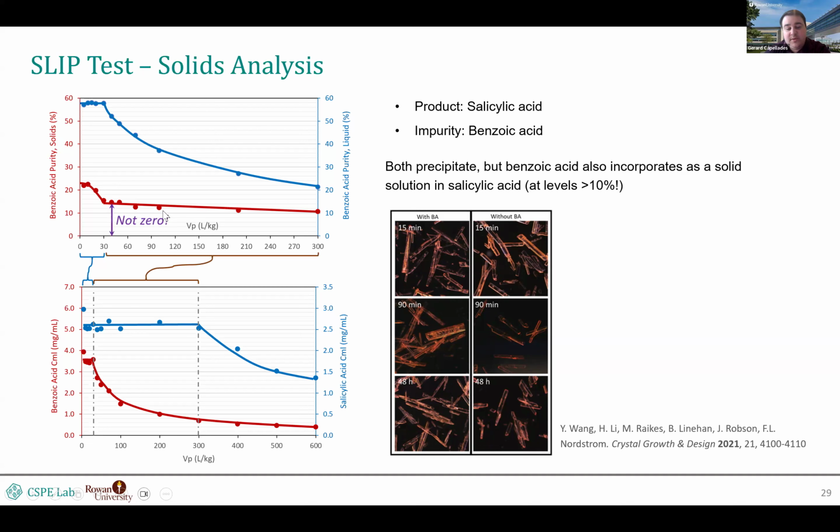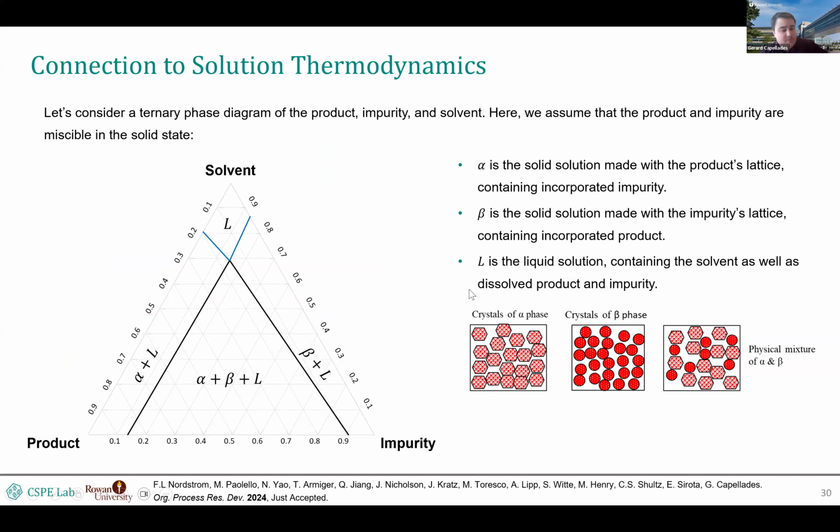This is one where you can basically validate, hey, I know that there are no impurities precipitated in my sample, but I do know that the solids are still 14% impurity, even when I correct for contamination from the mother liquor, right? And at that point, it's already telling you that there's some form of entrapment within that, right? It's a form of lattice entrapment. And this all has a thermodynamic basis.